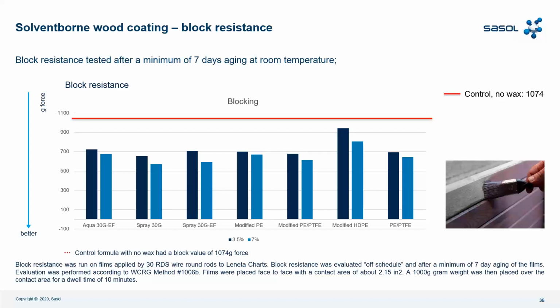So in this case, if you need a great block resistance, plus other performance of course, but the block resistance is very important for you, the suggestion is Spray 30G at 3.5% or at 7%, and you have an even lower, better block resistance. But these results show you that Aqua 30G-EF in any case is aligned with the performance, and also aligned with the competitor performance.